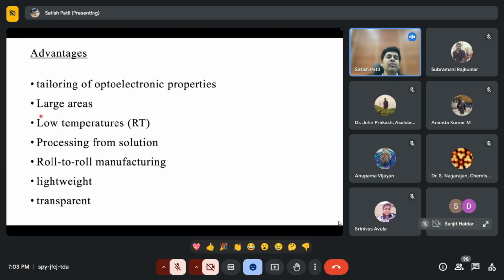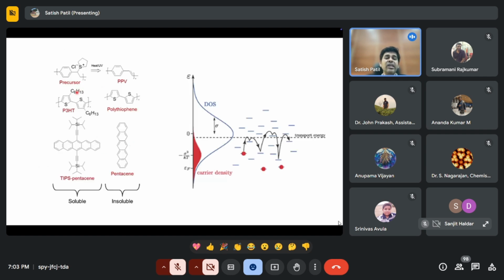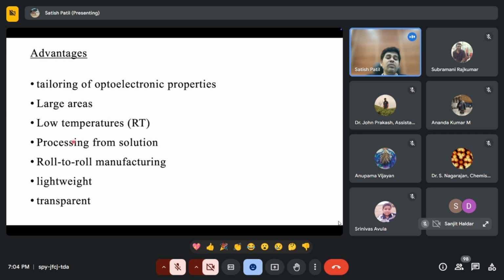Whereas when you make a device using a semiconductor like silicon, you have to process everything at very high temperature, above 1000 degrees. You can process from solutions. These materials are soluble, as I mentioned, because you can introduce such alkyl chains. You can dissolve these materials in any organic solvent, and then you can process from solution.